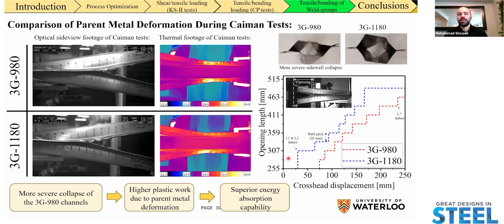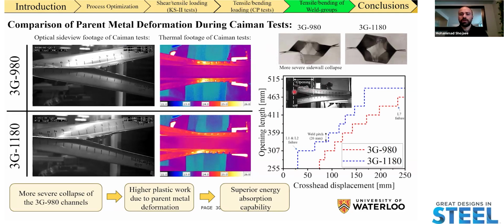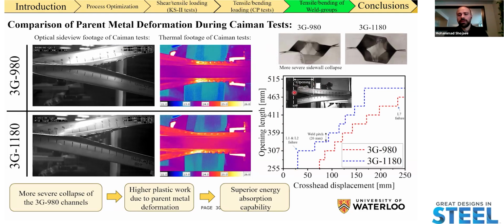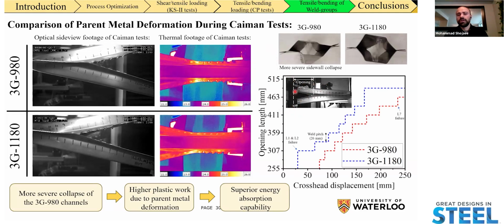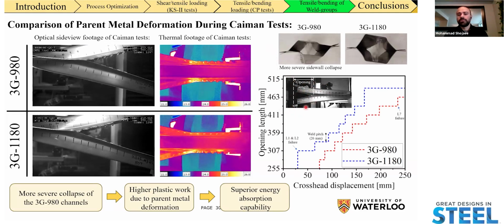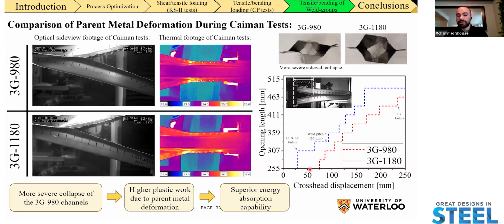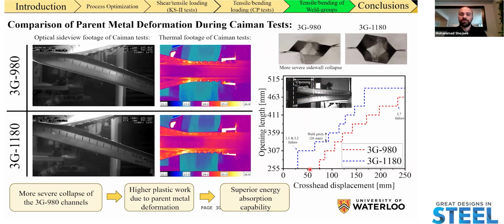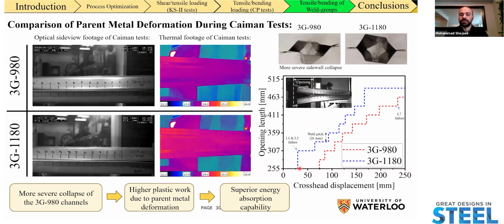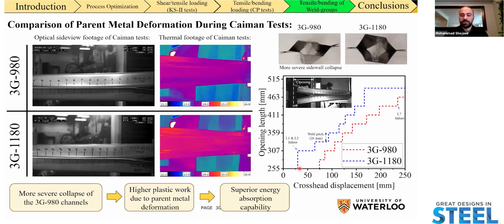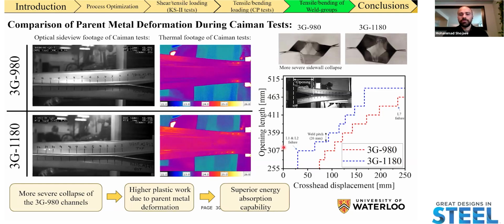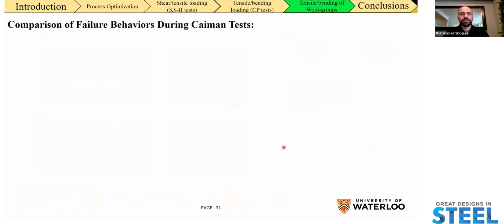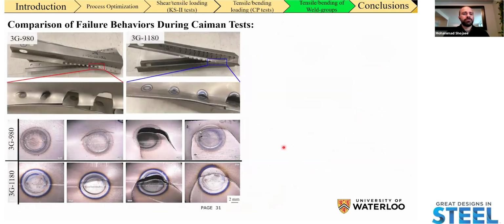But at the same time, when we look at the rate of failure that's happening throughout the different crossheads, we are using this index that we're referring to as the opening length, which is the length from the fixture to the first intact weld. And we're always seeing that the failure is initiating sooner for the 3G 1180 material at a lower crosshead displacement relative to that of the 3G 980 material. To investigate that more, we looked at the failure behaviors that we're seeing in these tests, specifically for the 3G 980 and 3G 1180.